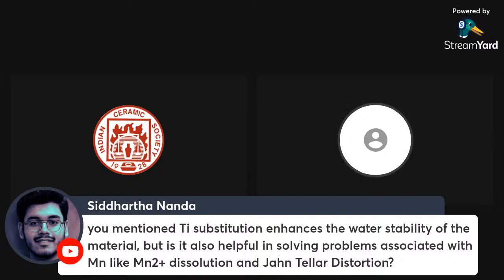of question. But as you also rightly pointed out, even if we do not want to get rid of the entire manganese, if we have part substitution of manganese with anything like titanium, it can still suppress the manganese dissolution, and especially it can render the Jahn-Teller distortion to be not a long range Jahn-Teller distortion. So it can minimize the overall distortion of the structure even if we substitute part of manganese with something else. So very nice question. Now again, as you also mentioned, the layers shrink. Yes, that's a very good question.